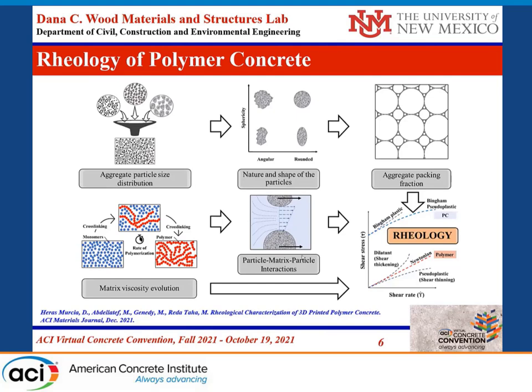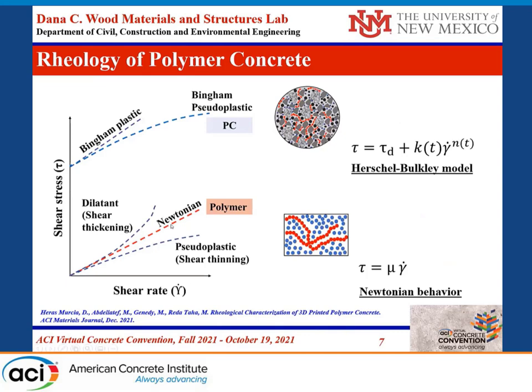It's important to realize that polymers at large exhibit Newtonian behavior with no thixotropic property, described by a linear model with zero yield stress. But when we add aggregate material and mix it over time, you start seeing thixotropic behavior of the polymer concrete, which can be described by a Bingham pseudo-plastic model. You can see the static yield stress and its evolution with time.